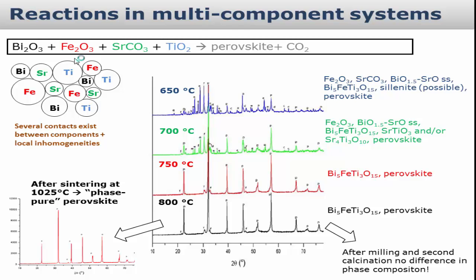Of course, as you increase the temperature, you will get a more complete reaction. At a certain stage, it will stop. That's related to a diffusion-controlled reaction, so it's diffusion limited. If you, for example, try to double calcine, it will not work. It will still have some secondary phases.